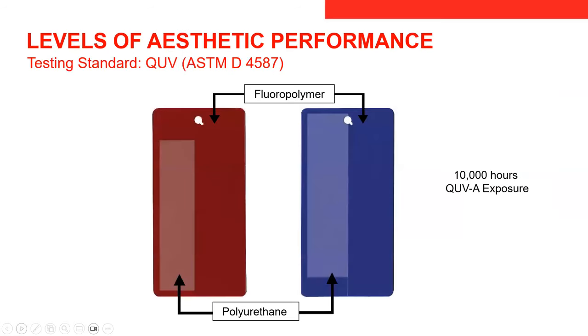And here we're just showing the level of aesthetic performance testing via QUV after 10,000 hours of exposure. You're seeing a fluoropolymer on the right on both panels versus a polyurethane, which is on the left of both panels. While the color hasn't changed much within the picture, you're going to see more on the gloss change that has happened with those. And Mark had mentioned that we're really focusing on how much gloss can play a huge factor in degradation of a coating system.